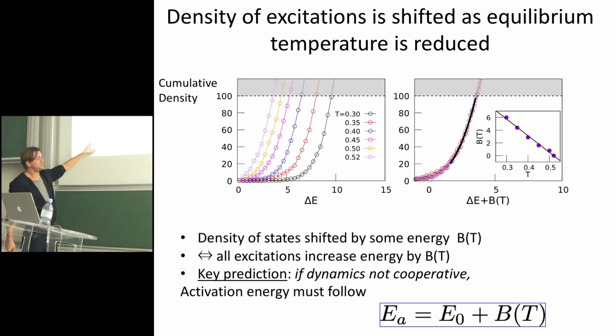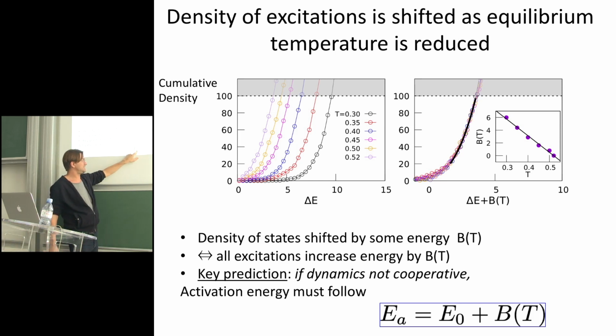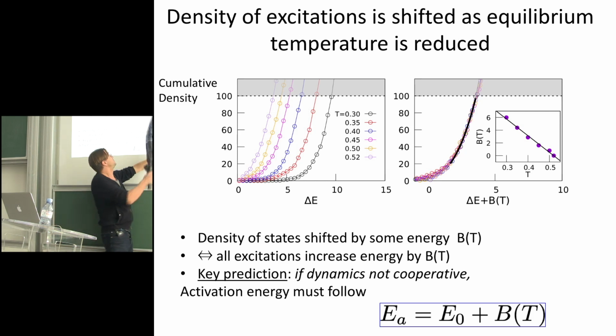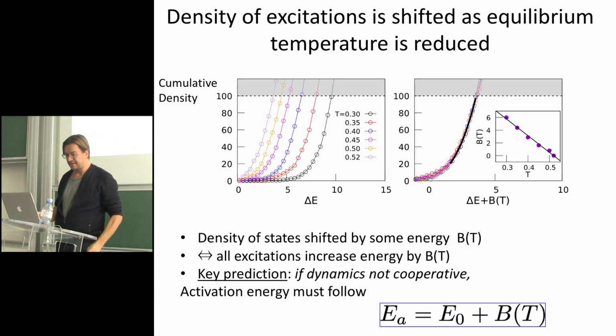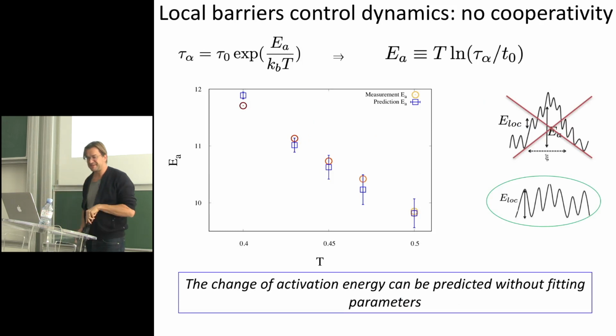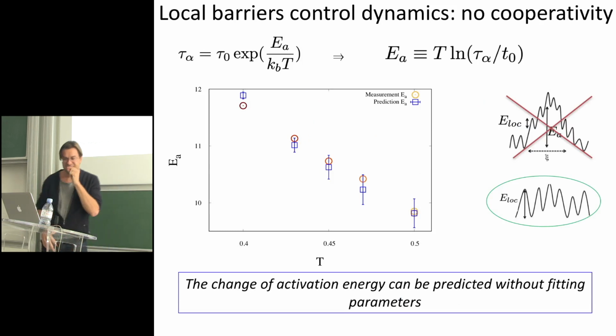Now, that's a powerful observation, because if you make an assumption that many in the field do not, those who believe in this cooperative model would not agree, but if you assume that the dynamics is not cooperative, it's only governed by barriers, then this observation fixes the fact that the activation energy, when you change temperature, has to increase by this shift. You don't know what the absolute value should be, but you know how it should change. So that's maybe the slide to remember of this presentation, is that this is something that you can test without any fitting parameters.